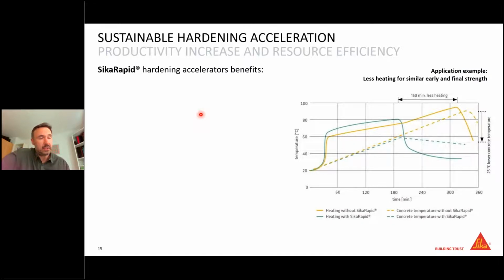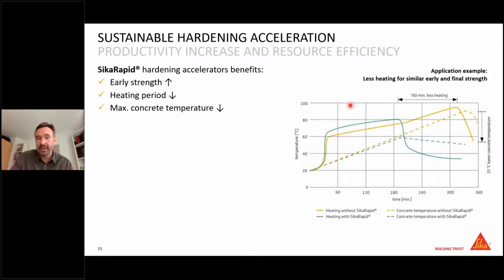Another interesting technology important for element production is Sika Rapid hardening accelerators. I have shown you an example on the right side where you see the temperature curve of a heating of a concrete element. The yellow one is the one without the use of Sika Rapid accelerator, and the green one is the one with Sika Rapid accelerator. You see that by increasing the early strength of concrete, it was possible to reduce the heating period significantly, at the same time reducing the maximum concrete temperature.